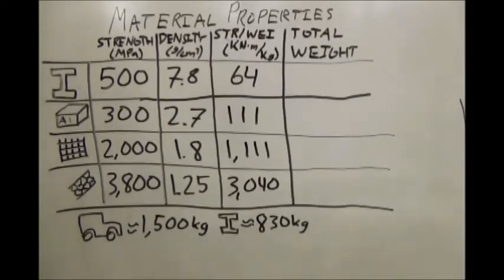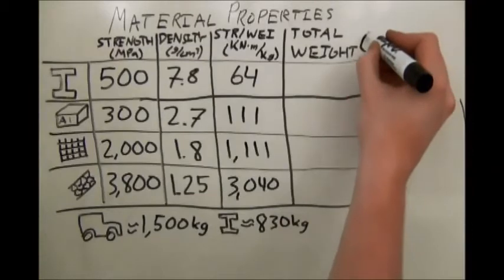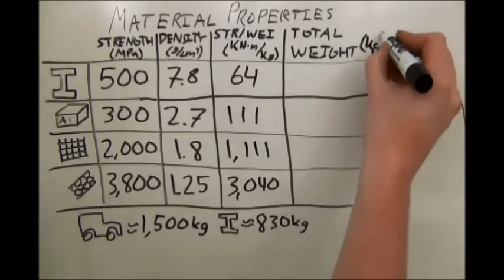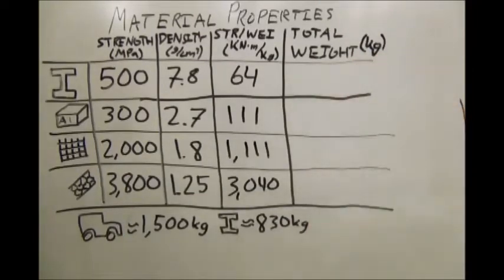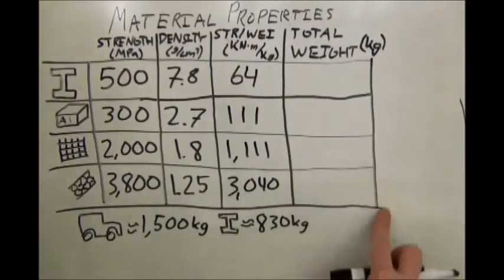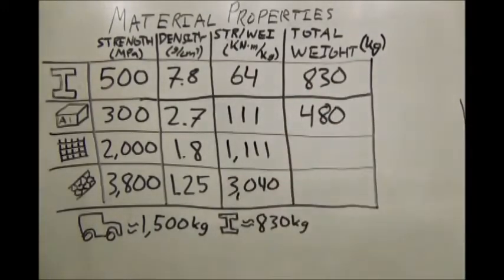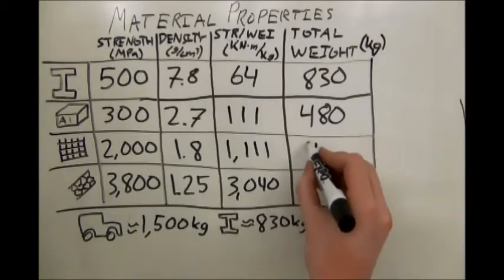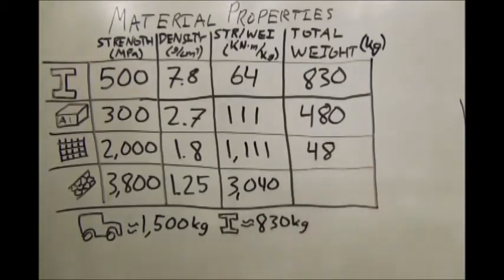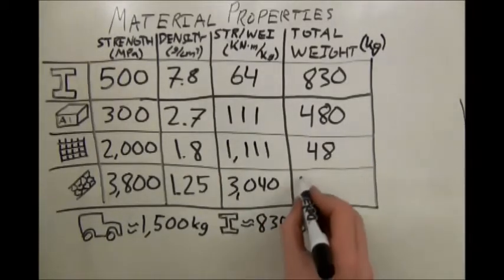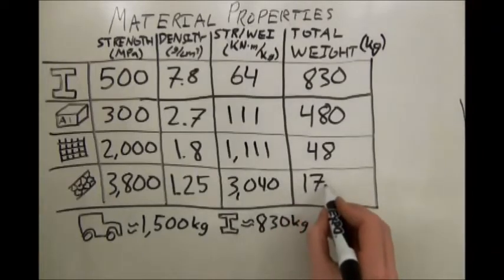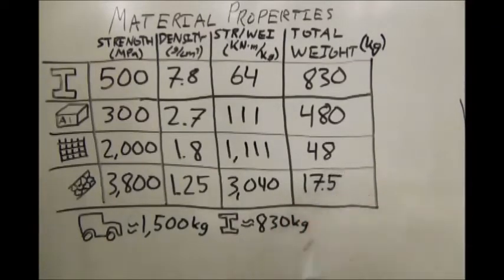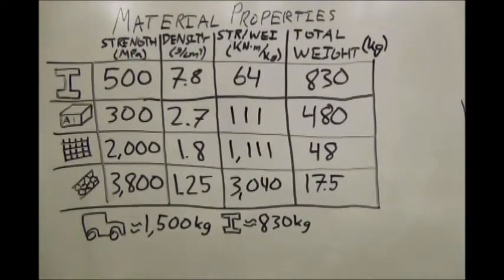If you replaced every single piece of steel in that 1,500 kilogram car with aluminum of equivalent strength, that 830 kilograms goes down to 480. Replacing every piece with carbon fiber reduces the value all the way down to 48 kilograms. And if you used the carbon nanotube composite discussed earlier, all those parts would weigh a mere 17.5 kilograms. The total weight of your car just went from 1,500 kilograms to 690 kilograms, just by using engineering composites.